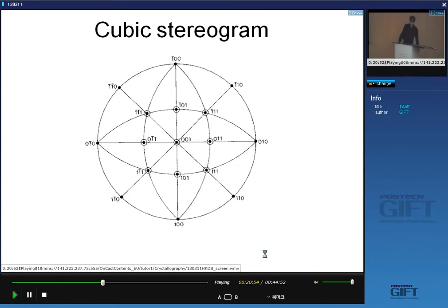So if I do that for a certain number of planes, then this is the stereographic projection of a cubic crystal. You can see 0, 1, 1 there and 0, bar 1, bar 1 underneath there. Okay, these are the edges. So this is the 1, 0, 0 pole, the normal to the 1, 0, 0 plane. This is the normal to the 0, 1, 0 plane, and this is the normal to the z-axis. So these are all the cube edges, basically, aren't they? 0, 1, 0, 1, 0, 0, and 0, 0, 1.